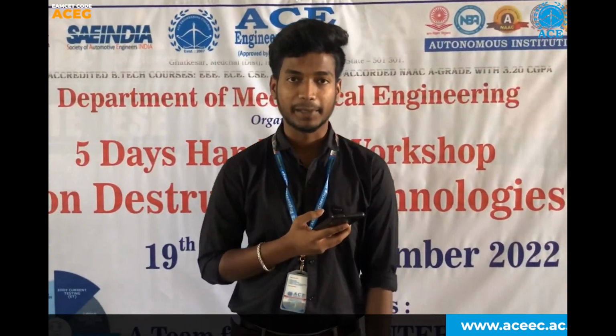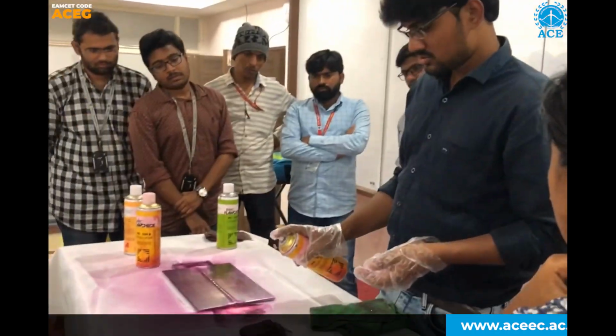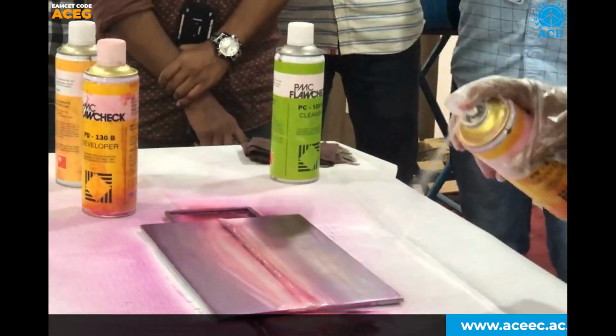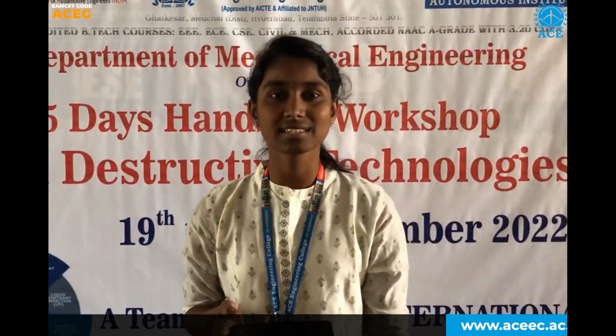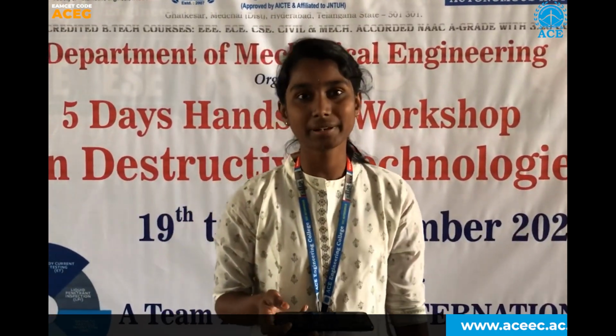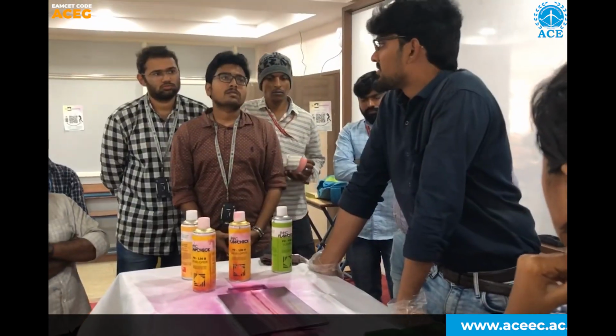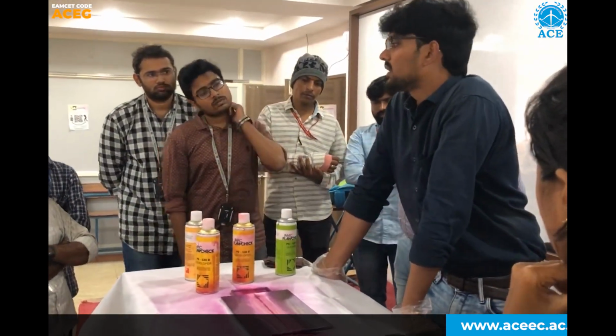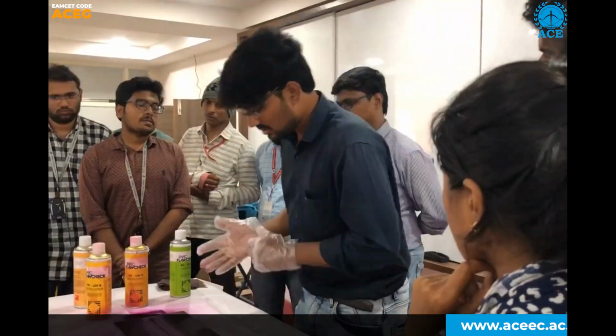After removal of excess penetrant on the material, we apply the developer. The developer color is white. Next process is inspection. After applying the developer, visual inspection should be done immediately, up to 7 minutes. It takes 7 minutes for the developer to draw the penetrant out of the material.